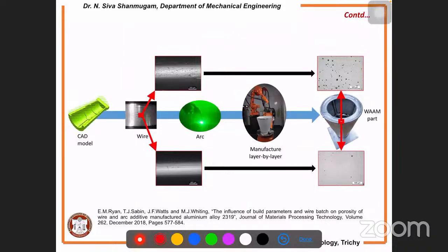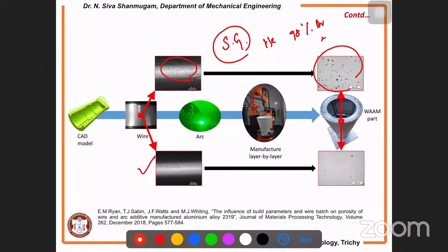Sir, when I investigated this filler wire, you see a lot of porosities, so the final product also ends up with porosity. Selection of the material is another factor, and so is the selection of the shielding gas arrangement, whether helium is required or a combination of gases. If I'm using stainless steel, I use 98% argon plus 2% carbon dioxide. If you use a different shielding arrangement, you can easily control the weld defects. Normally we do not use the word impurities, we say weld defects. You can make the defects very close to zero, not perfectly zero because porosity is inevitable. You can suppress it to less than 3%.